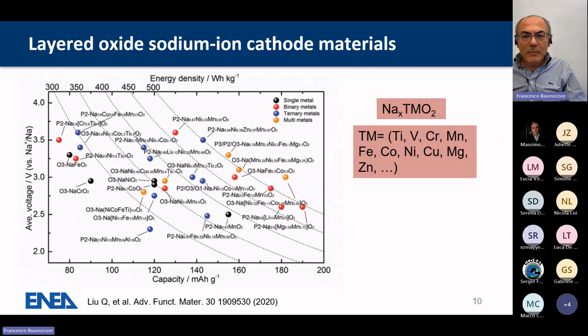In this plot from a review, we see different cathode materials with different compositions. The typical formula of the layered oxide sodium-ion cathode materials is a fraction of sodium, one or more transition metals, and oxygen. When you put in this formula just one transition metal, for example manganese, you have a single metal oxide. In this plot you see the performance of different materials. For example, the black dots are the single metal oxides, and when you insert manganese, you are here.